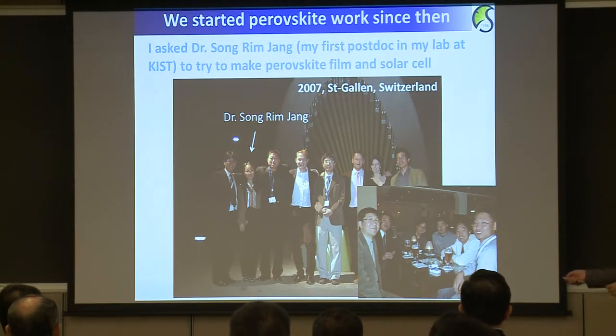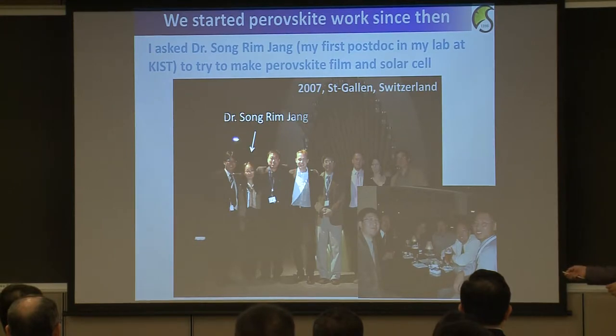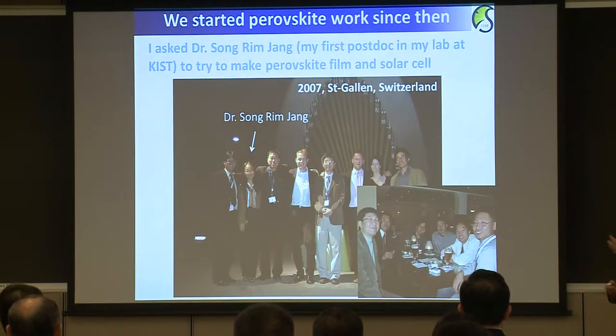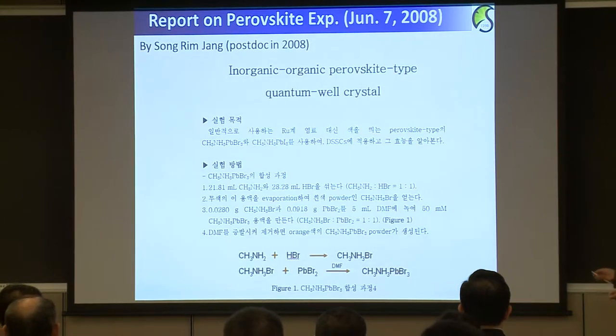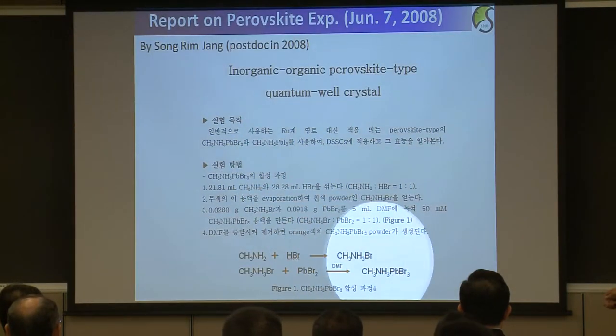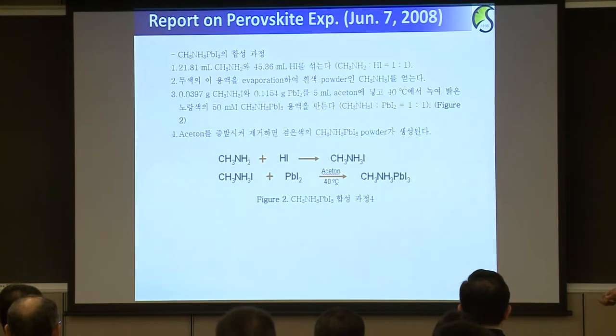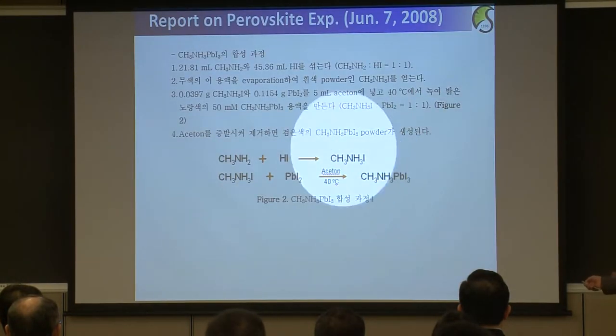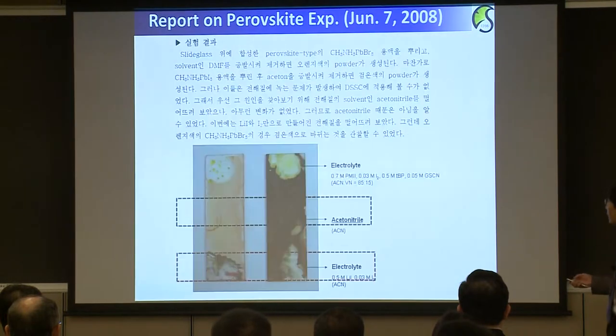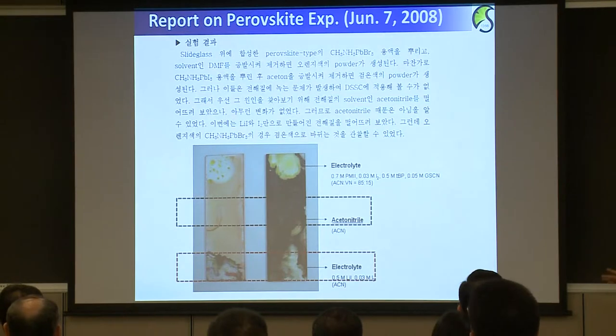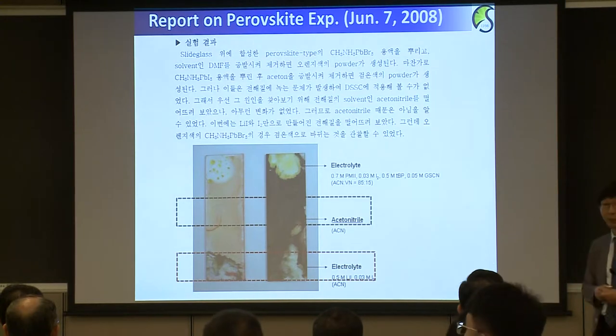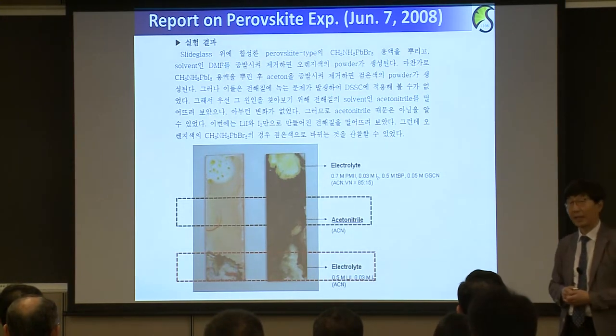And I had a postdoc, Dr. Song Rim Jang, and I asked her to work on the perovskite sensitized solar cell. And then she actually prepared methyl ammonium lead bromide and also methyl ammonium lead iodide in powder form. And then she made some coating solution with this powder, and she deposited bromide and iodide perovskite on the plain glass substrate.